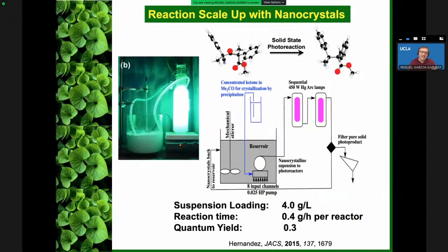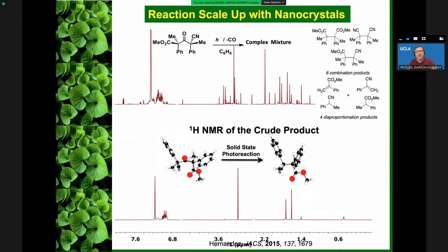And this is how they did it, right? So they devised a reactor that has basically the opportunity to pass the light through the suspension, through a reactor, and then through multiple passes have a really efficient reaction. When they collected this product, what they saw is that the test sample in solution in the top, as you can see, the NMR spectrum has literally dozens of products, meaning that it has dozens of different peaks from different products, a very messy reaction when you have a high entropy system, many configurations, many opportunities for reactions to take place.